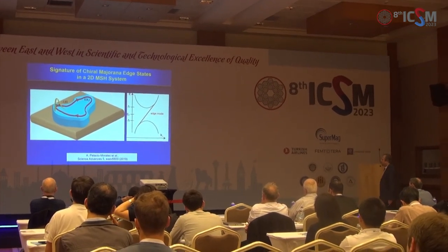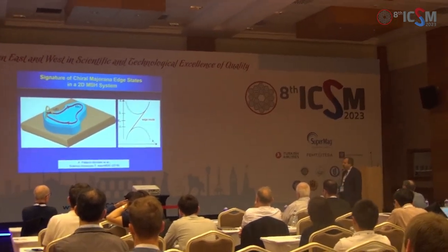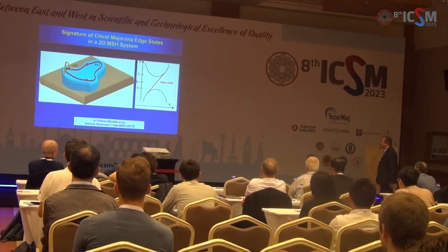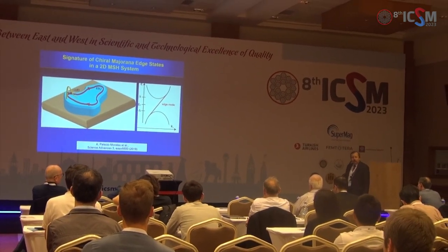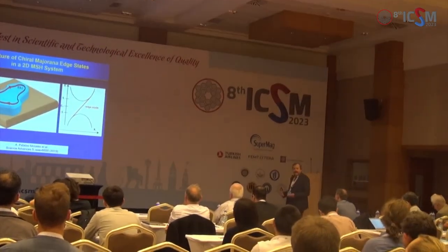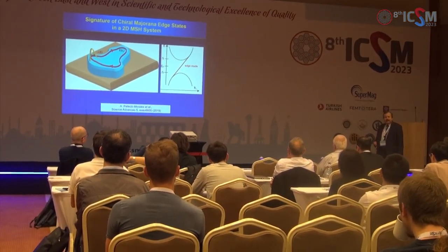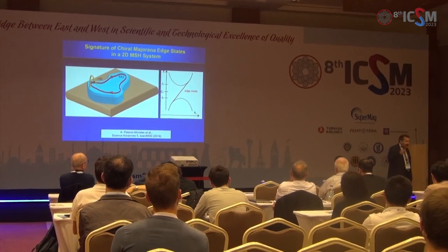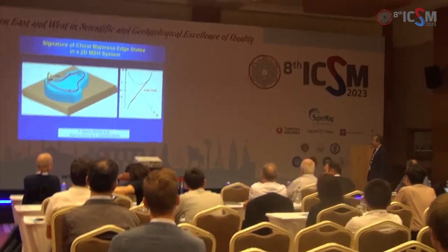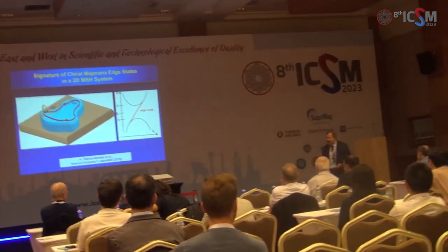We wanted to look at this exciting proposal from the experimental side, and it turned out that the theory was interesting as a starting point and motivation, but what was proposed—using lead—did not work out at all. Why? Because lead, as every surface scientist knows, is a surfactant, meaning if you want to grow iron on top and anneal the system, lead always wants to go on top. That would never work—that's the difference between theory and experiment.